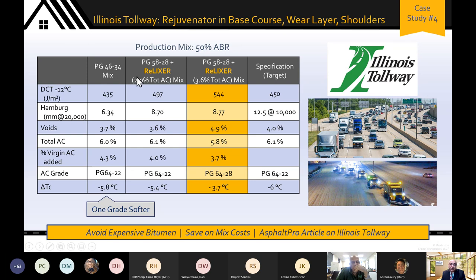Again, a couple of cases. Remember I told you, one grade softer, a mix made with one grade softer. This is PG 46-34. The more common grade of bitumen used is PG 58-28. So this column is properties of the mix made with rejuvenator. And as you can see, they were looking at DCT as their fracture toughness, Hamburg as their rutting parameter, and trying to compare with specifications. The added wrinkle here, delta Tc. I did indicate to you, and we'll have some more slides on this, it is almost mandatory, and we recommend this very highly, that it's good to make a mix on day one and meet all the properties. You want to make sure that that mix is going to last as a function of time.